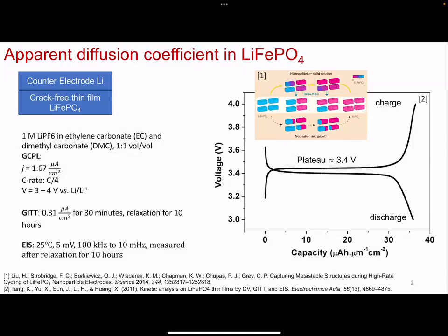And so in a traditional lithiation and delithiation process, you have nucleation of the secondary phase, and then eventually it transforms. So it goes from this blue, there's some nucleation, and then there's a phase boundary front that evolves, and then you achieve your secondary phase that you see here in this hot pink, and then everything becomes hot pink. So it becomes the other phase.